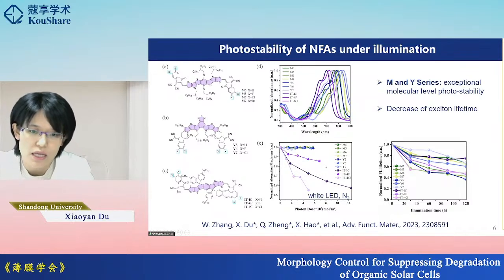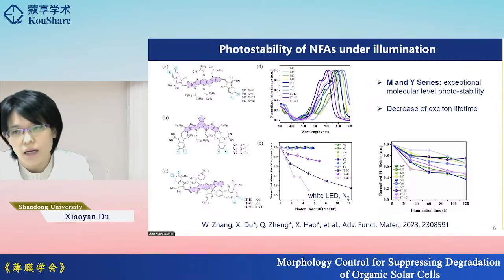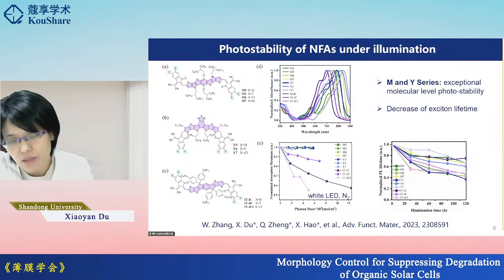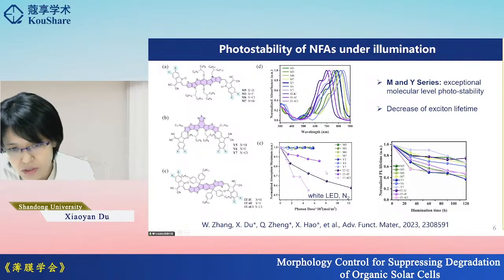Here we show the result of the stability measured by UV-vis absorption spectra. So we can see that both the M series and the Y series, under the same conditions, show exceptionally stable properties compared to the IT series. And this is related to the conformational stability of the materials, or photochemical stability, under illumination in a nitrogen atmosphere without the photooxidation effect.